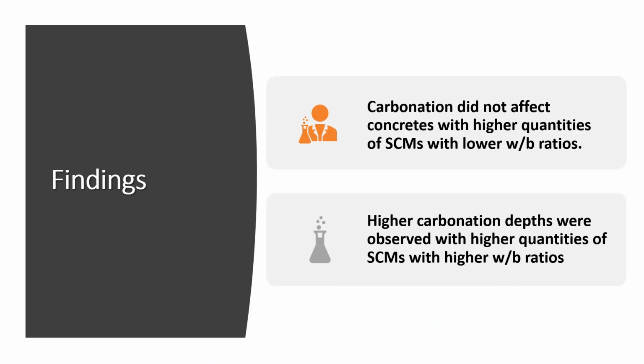What are the findings? The findings from this investigation are like this. Carbonation did not affect concretes with higher quantities of supplementary cementitious materials with the lower water binder ratio. Higher carbonation was observed with the higher quantities of SCMs with higher water binder ratios.